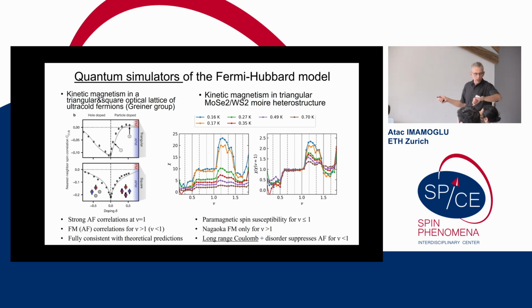So I thought that I'd finish by comparing it to a parallel experiment that was carried out by Markus Greiner's group in a very controlled experiment, right? So this is cold atoms. They can actually control everything, but they only have on-site interactions, right? So they can go from square to triangular lattice. And indeed, in their case, they're dominated by the superexchange, which actually is reduced as they move away. And in the triangular lattice, they see this tilted curve, and they attribute this to kinetic antiferromagnetism, even though the effect is prominent. The strongest antiferromagnetic correlations, which they measure with their microscope directly, is at nu equals 1. And this is our result, and you see that their result is fully consistent with theoretical calculations.